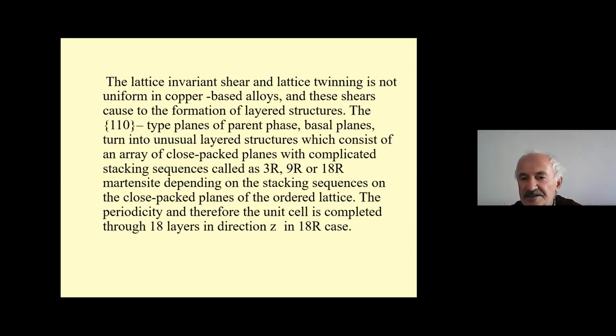Lattice invariant shear and lattice twinning are not uniform in copper-based alloys, and these shears cause the formation of layer structures. 110 type planes of the parent phase turn into an unusual layer structure, which consists of an array of close packed planes with complicated stacking sequences, called 3R, 9R, or 18R martensite, depending on the stacking sequences on the close packed planes of the ordered lattice. The periodicity, and therefore the unit cell, is completed through 18 layers in the case of 18R martensitic structures.